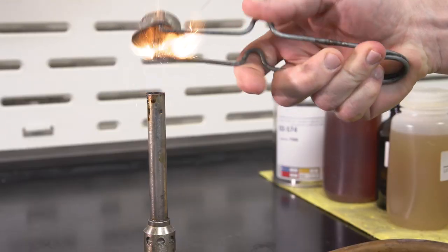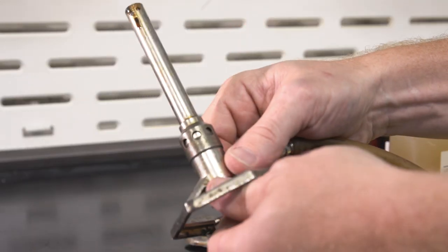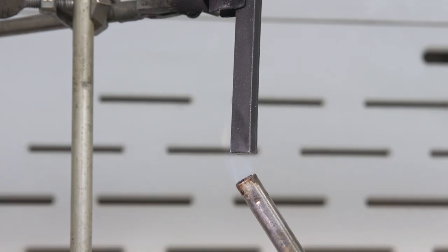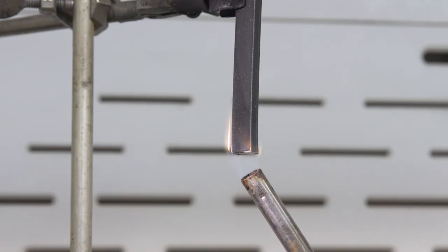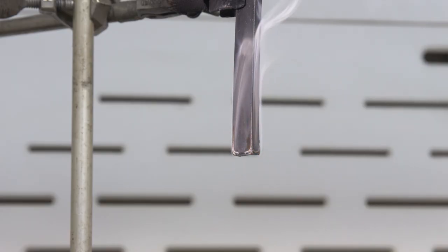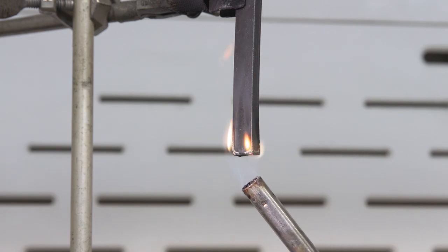And all of these would be classified under what, UL 94 V-0? That is a vertical flame test where you actually have to take a very small square. So you put surgical gauze underneath it. Yep, and if the gauze lights. You put a flame underneath this and you take it away, and it has to go out two different times in less than 10 seconds.